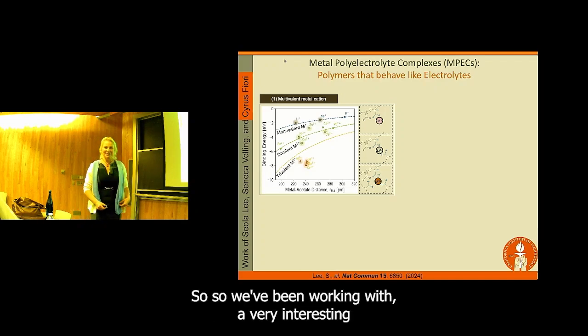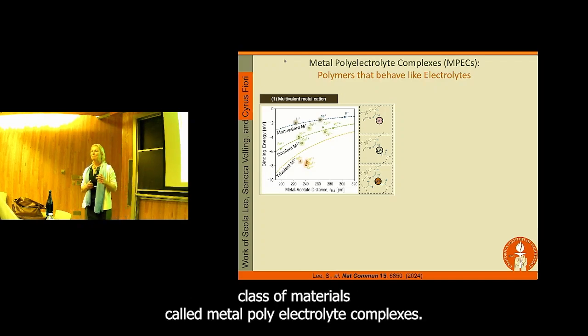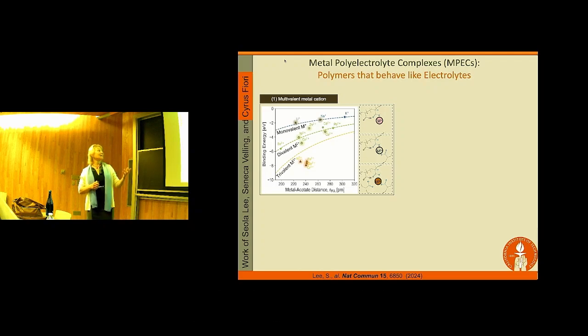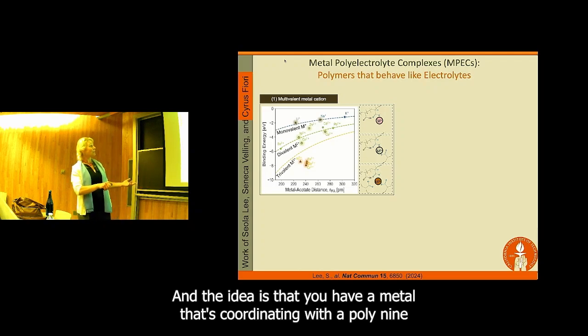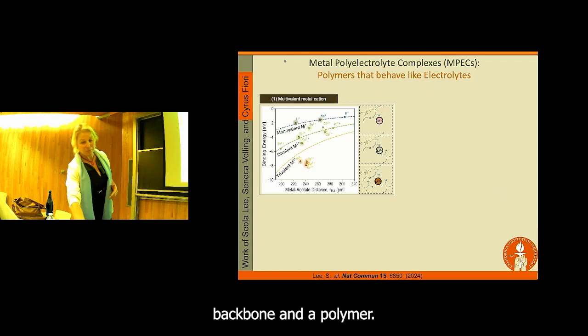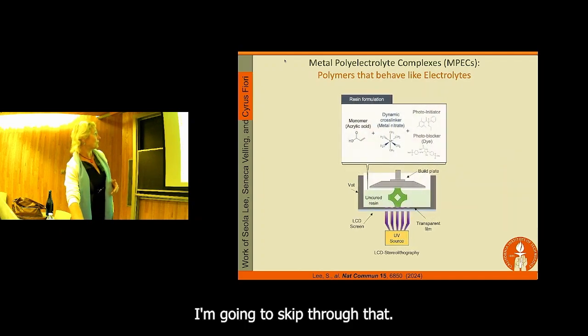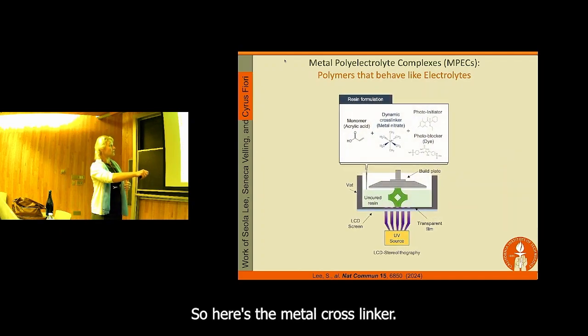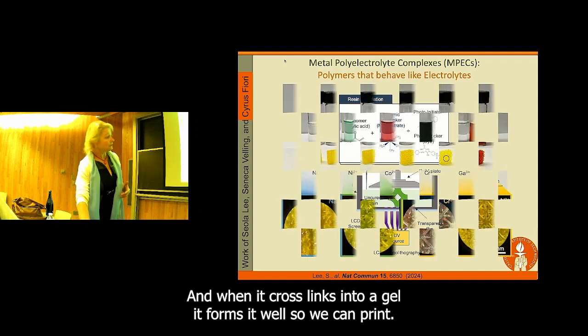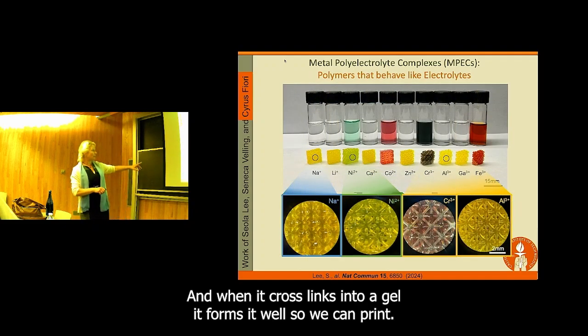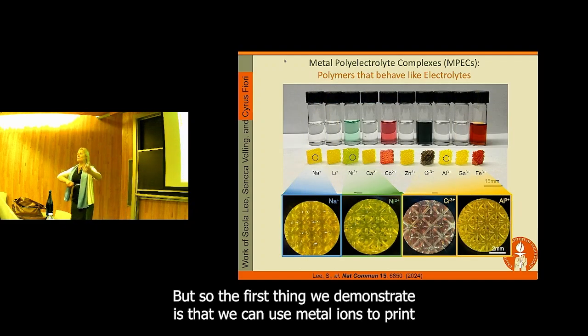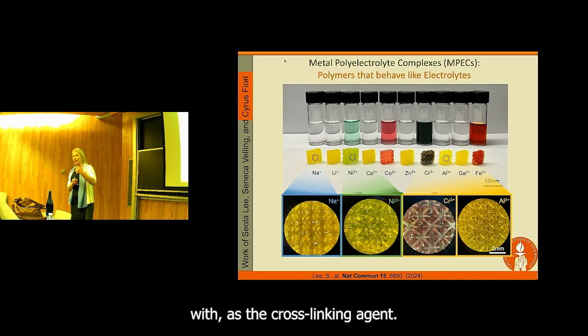Okay, so we've been working with a very interesting class of materials called metal polyelectrolyte complexes. The idea is that you have a metal that's coordinating with a polyanion backbone in a polymer. I'm going to skip through that. So here's the metal cross-linker. And when it cross-links into a gel, it forms, so we can print with it. So the first thing we demonstrate is that we can use metal ions to print with as the cross-linking agent.